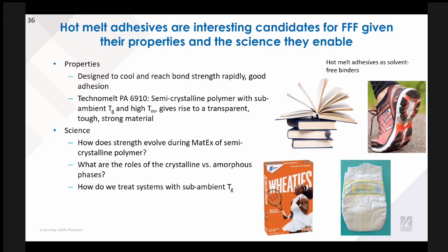And so in this work, we've been looking at Technomelt PA, which is a semicrystalline polymer that has a sub-ambient Tg. That means that at ambient conditions it's rubbery, but it has a high melt temperature, and this combination gives rise to this transparent, tough, strong material.